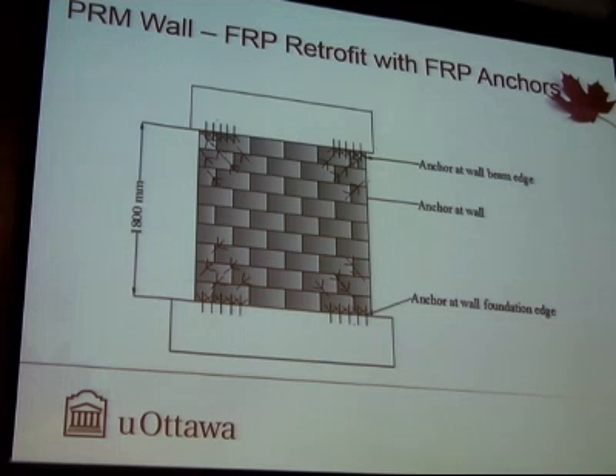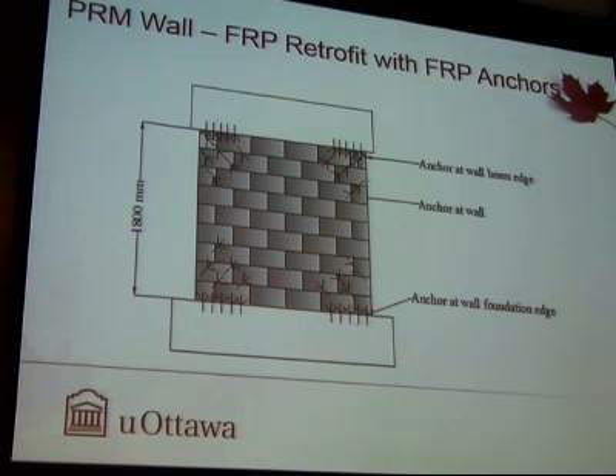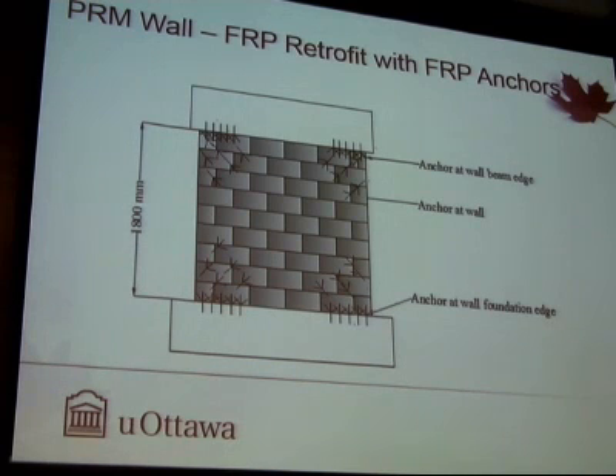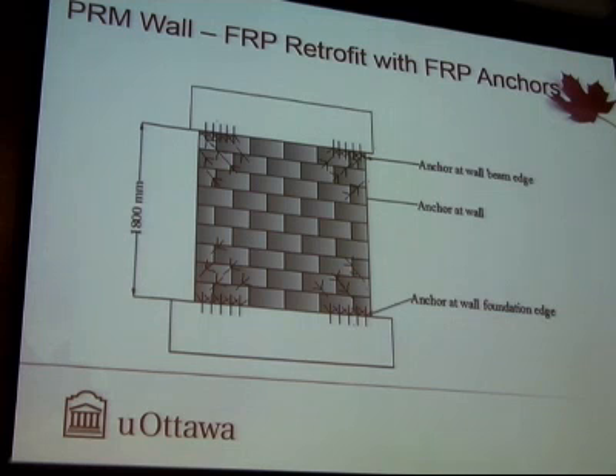Finally, I'd like to show you two applications of surface-mounted FRP on masonry walls. The first one is, again, partially reinforced, nominal reinforcement, and we used FRP essentially to control shear as well as introduce some flexural capacity, because in earlier tests we saw that shear would follow immediately after rocking, and then there would be diagonal tension and toe crushing in masonry. So we essentially wanted to have diagonal elements in FRP, and then we also wanted to connect vertical FRP to foundation for flexural strengthening, and hence we used the same anchors in the way it is shown.